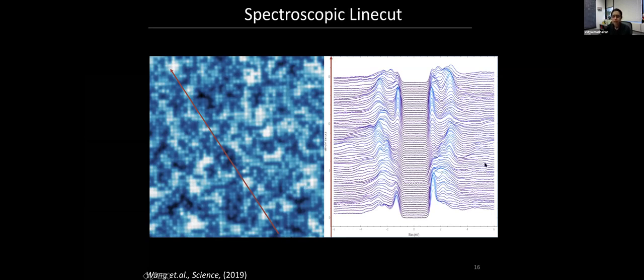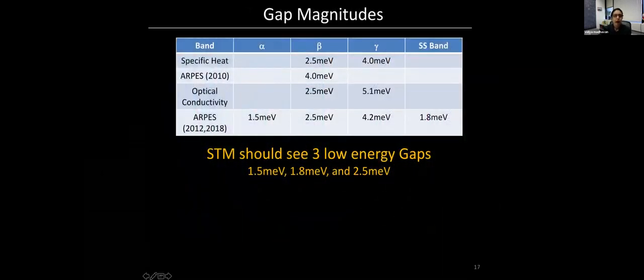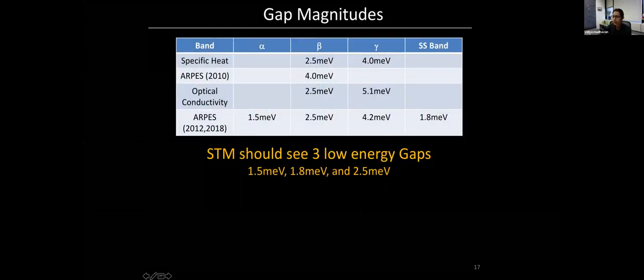Now, this here is a line cut. It shows you spectra taken along this line. And what you see immediately is A, there are multiple coherence peaks, right? You can see one here, and so on. And B, these coherence peaks actually shift around as a function of position. So it's obviously electronically inhomogeneous, and there are multiple gaps. And these multiple gaps come from these various pockets that I was talking about earlier that cross the Fermi energy.